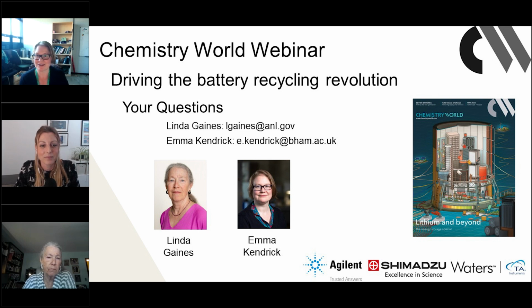So maybe if I go first and then pass over to Linda for comments as well. So particularly for automotive applications, the battery packs are really highly engineered, and the cells are cycled to a certain percentage of their initial capacity. So typically 80 or 70% is put on them, which means that by the time they end, they still have 70% of their energy available within the cell.